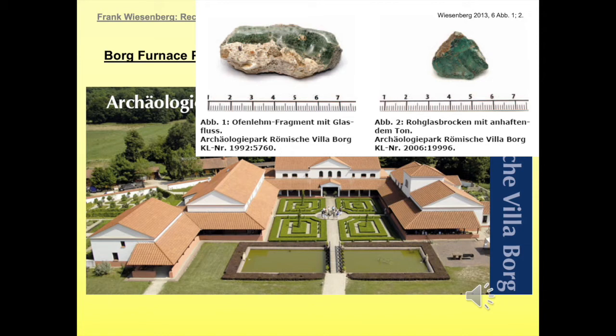A lot of building material was excavated over there. For instance, picture number 1 shows a highly fired daub with a pretty thick layer of molten glass on top. This is one example of building material from a glass furnace. And in the picture on the right-hand side, there is a raw glass fragment, which probably derives from a glass pot, a melting crucible.